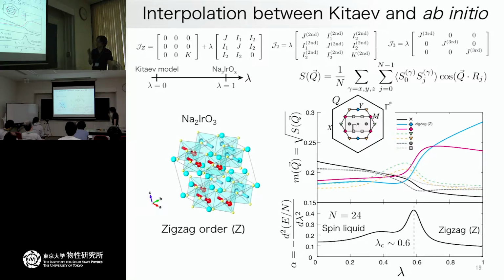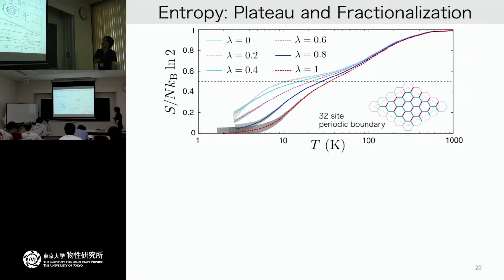And if you calculate the second derivative of the ground state energy with respect to lambda, then we find this kind of peak structure around lambda of 0.6. This signals a second order phase transition from the spin liquid to the zigzag order. And if you look at the square root of the structure factor, it corresponds to the magnetization, or an estimation from the finite size system. Then around 0.6, we have a rise in this zigzag order. Here our magnetic structure factor has a Q momentum dependence, and I am just picking this typical momentum. Here, this blue momentum represents the zigzag order found in the experiment. If you track this curve, it rises around this coupling constant, and it gives us the signature of magnetic order in the thermodynamic limit.